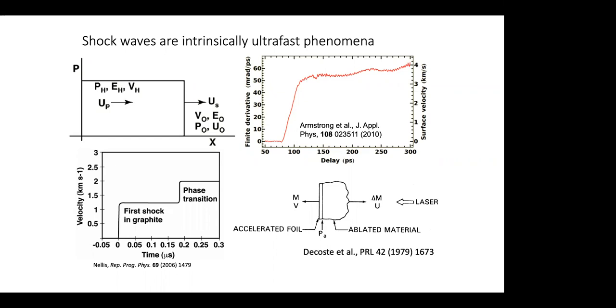It's just plain plasticity. So there aren't a lot of different phenomena that are involved in the state change. But if we're looking at a more sophisticated kind of material or more sophisticated mechanisms, like for instance, a phase transition, then we might see something a little bit more complicated, like for instance, a two shock situation where there is an initial shock to get to just below a phase transition pressure in a material, and then another wave associated with the actual phase transition itself to the final pressure.